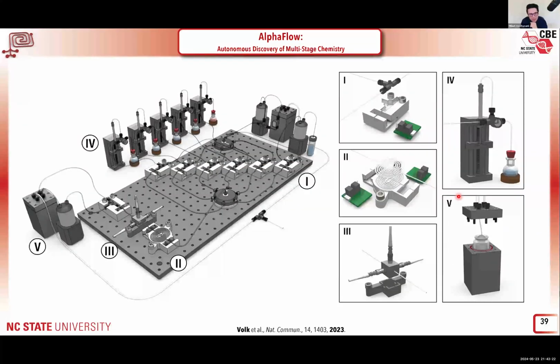It's very, very difficult. So to tackle this, we designed the hardware of our autonomous fluidic lab to work with the single droplet format that I introduced in the beginning of the talk. But then we have this modularity that enables the hardware of this colloidal ALD setup to automatically have access to different precursors. So the setup can automatically select precursor 1, 2, 3, 4, 5, or so on. And then it can do any injections on demand. And then we have the synthesis module, in situ characterization, and even purification. But the most important thing here is that everything happens within only a 5 microliter droplet. And everything is automated, so we can do up to 10 cycles of colloidal ALD. And we use just a few pumps to control the whole operation.